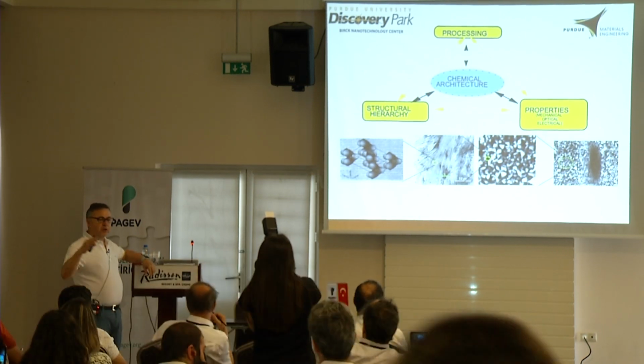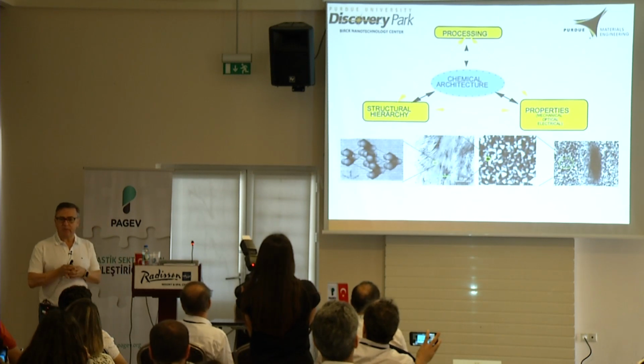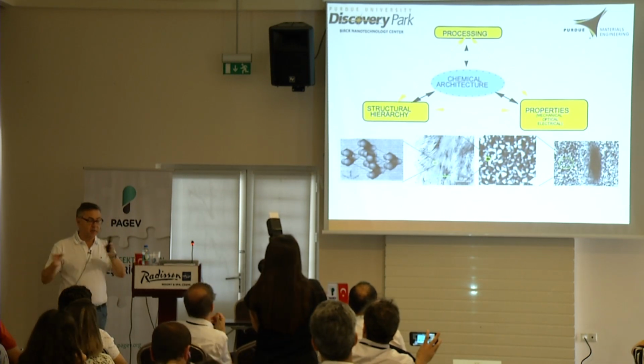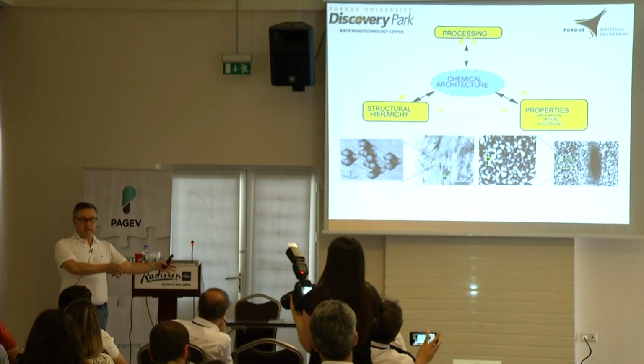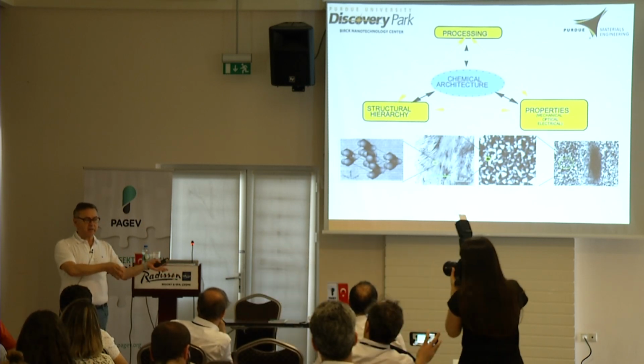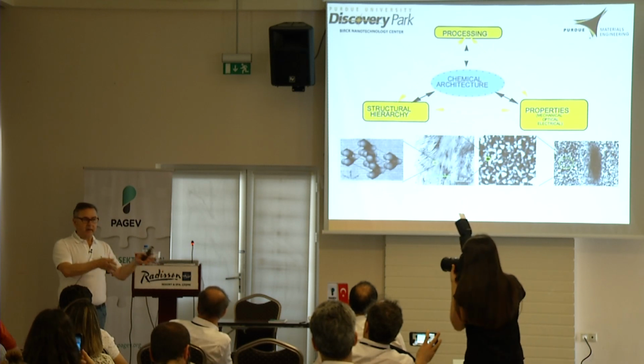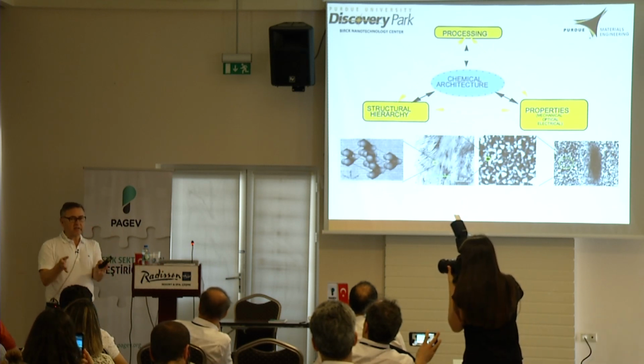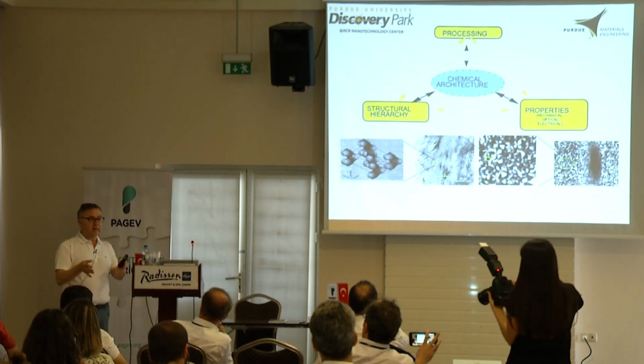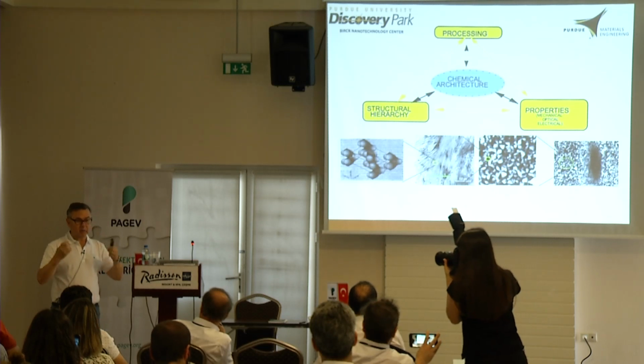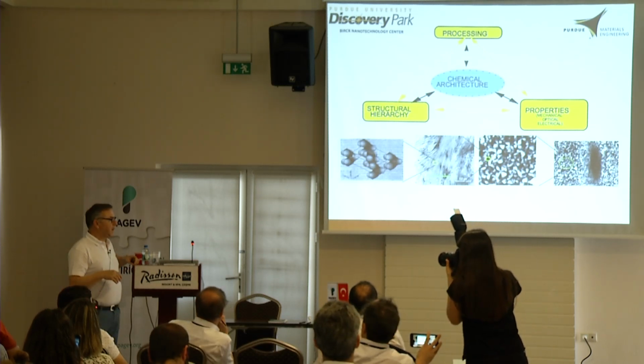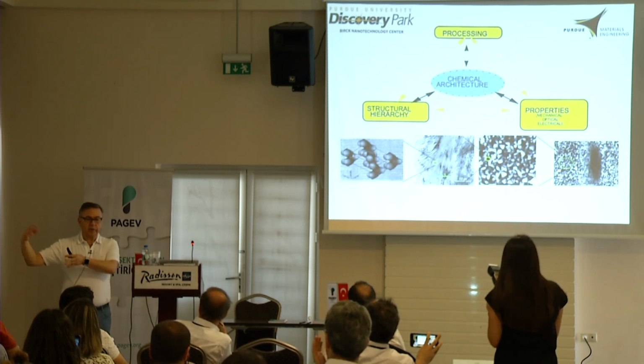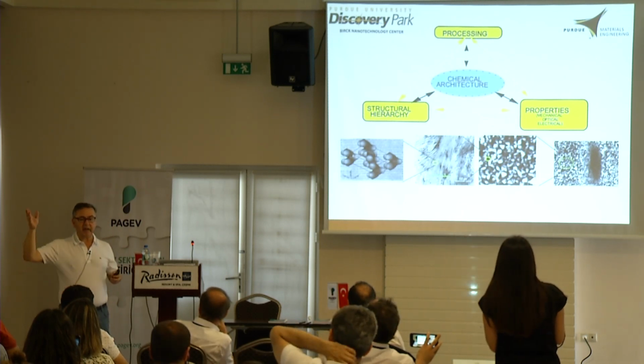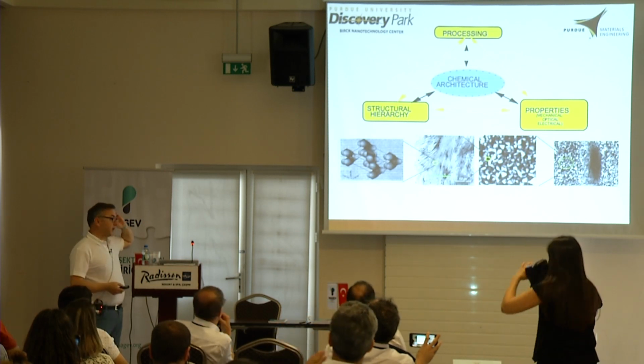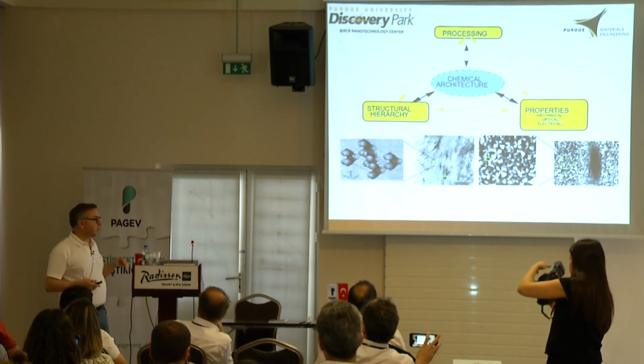And there is a third category. We really categorize the polymers from a processing point of view in 3 different categories. Polymers that never crystallize: polystyrene, ABS, polycarbonate. And polymers that slowly crystallize: polyester, PET, PEEK, polyphenylene sulfide. Those are very rigid molecules. And there are very flexible polymers: polyethylene, polypropylene, polyoxymethylene, and so on, that have Tgs well below room temperature. Because of that, they always crystallize, and because they are simple molecules.